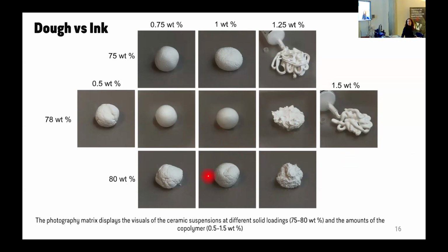And if you add so much ceramic material into the system, then the amount of polymer is not enough to cover the ceramic particles. You end up with surface cracks and such. So whenever we are choosing a system, we support ourselves with electrokinetic characterization and rheological characterization, but at the same time, this visual matrix. So I used to do these ceramic inks.